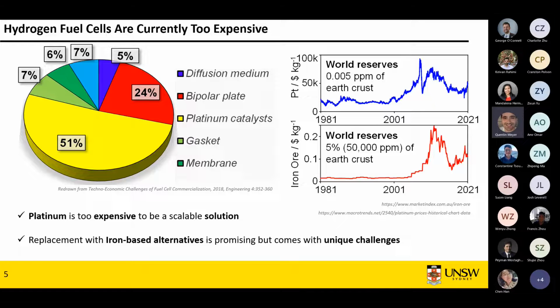What we've got is other metals such as iron. If you look at the price of platinum, you're at about $100,000 per kilogram. Look at the price of iron ore, you're at $0.2 per kilogram, so a million times cheaper. The good thing for chemists and chemical engineers is that iron-based materials have an affinity for the oxygen reduction, so they are a good alternative to platinum.